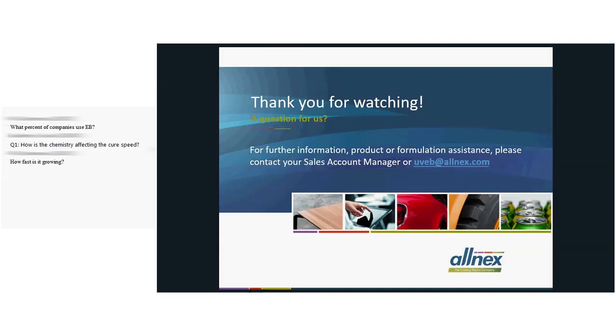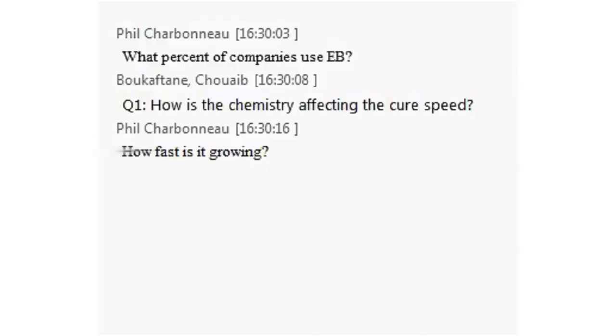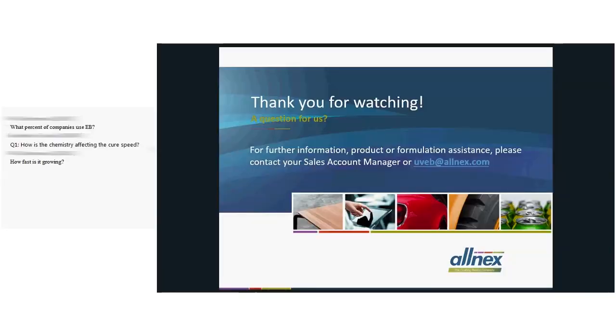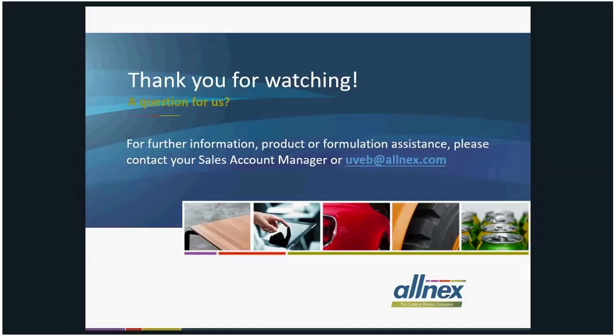It could quite possibly be better. Most soft touch formulations that I'm familiar with require the addition of some kind of particle, either organic or inorganic. And if the particles that you're using to generate that haptic feel have a strong absorbance in the UV, then electron beam would certainly be a better choice of cure technology than UV would.